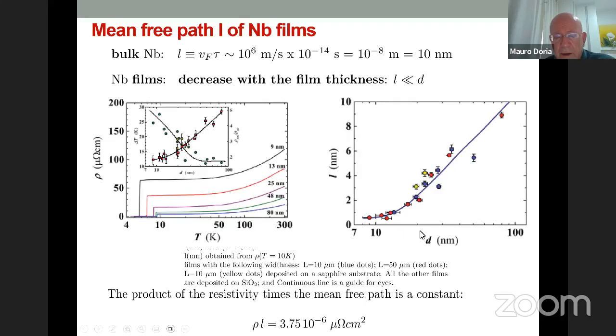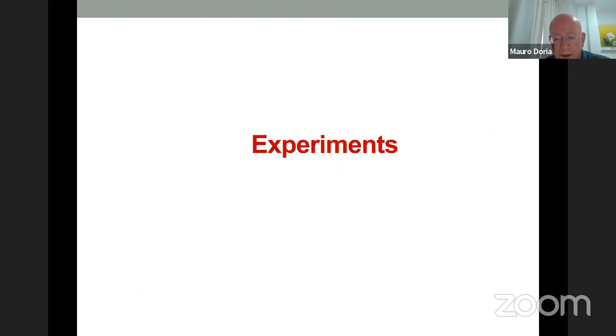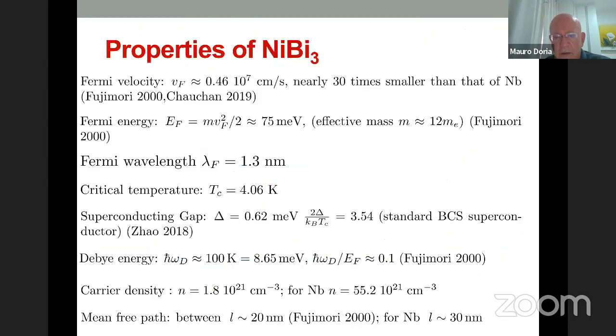You see here the mean free path is smaller than the thickness for niobium. So if you have a film of 10 nanometers, we have a mean free path that is smaller than that. So the electron, when it goes from one side of the film to the other, like a string, like a chord that kids play, that model doesn't work because you have many collisions. The electron has many collisions when it goes from one side to the other. Okay, so here we are.